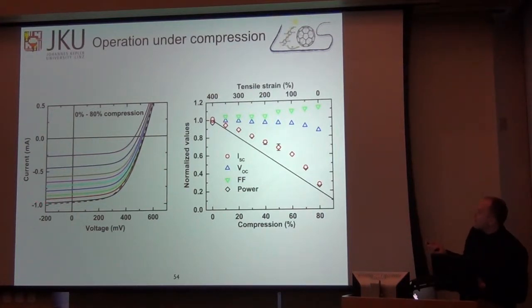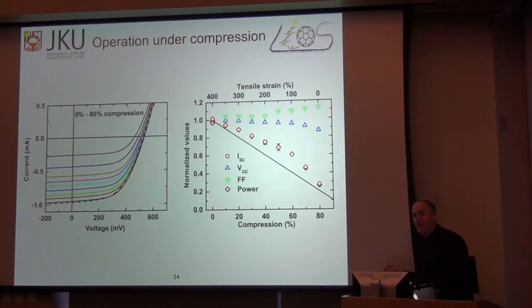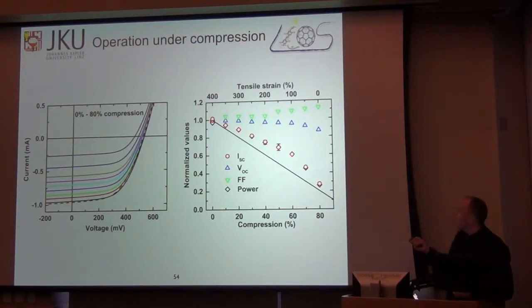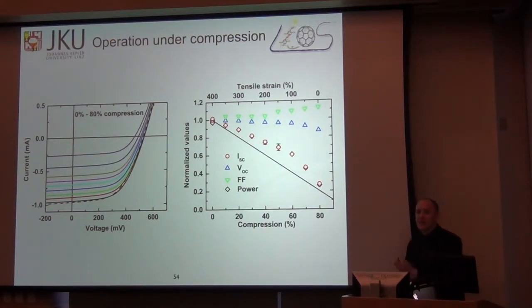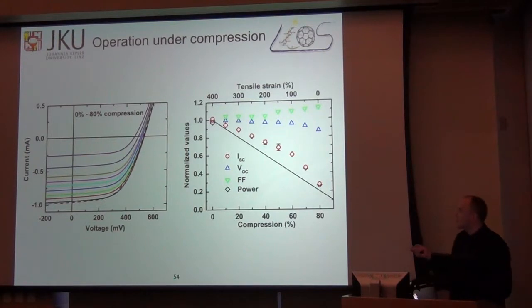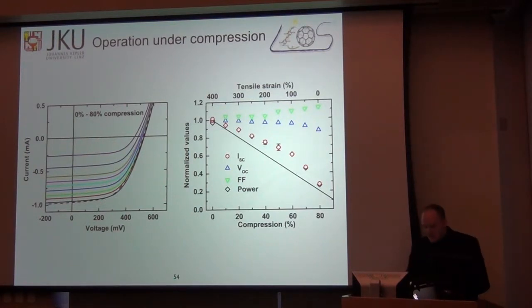You can see here the photovoltaic device parameters, the short circuit current, the VOC, the fill factor, and the power that you get out of the device, plotted as a function of the compression ratio. And the solid black line is what we would expect based on the incident area change. And the power always tracks slightly above that. That's simply due to the fact that when you're putting less current through the resistor, you get less voltage loss in the resistor, so you get slightly better power through the device.